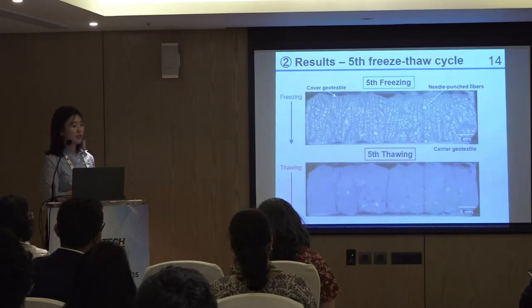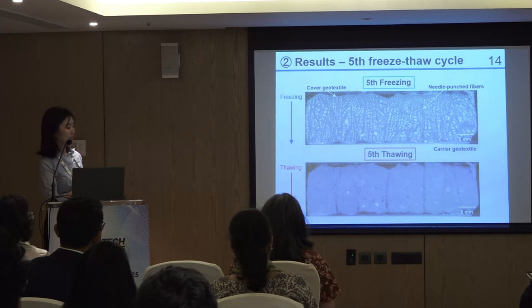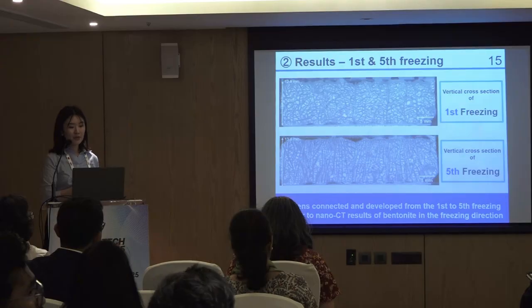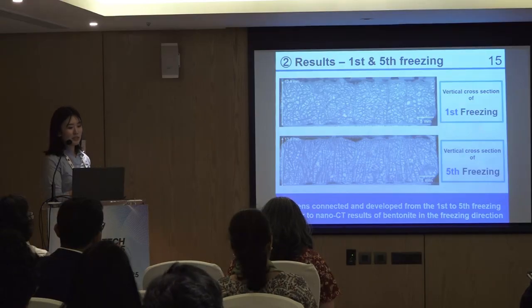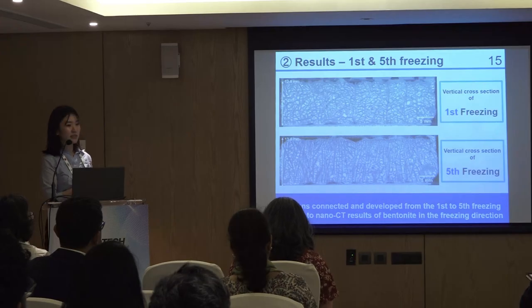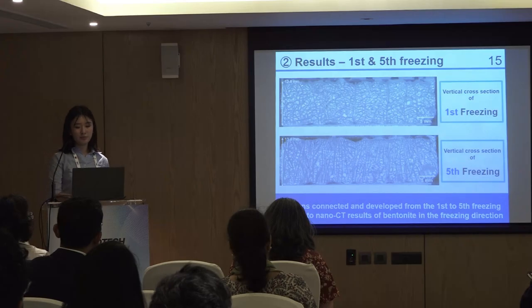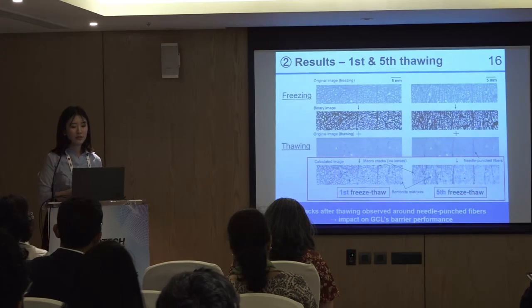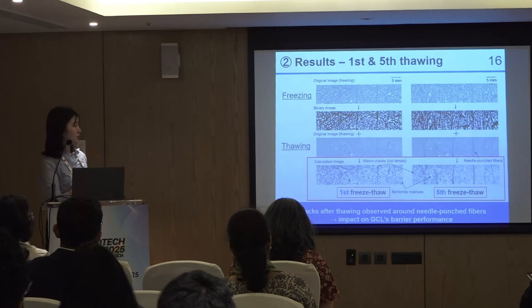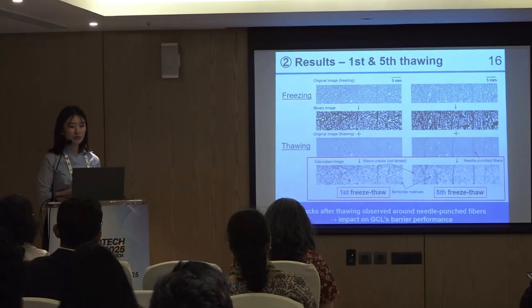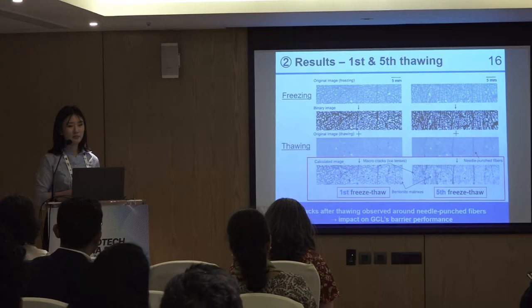And here, these are the images after the fifth freezing and fifth thawing. From the first to fifth freezing, frozen GCL showed a distinct ice lens pattern along the vertical freezing direction, similar to the nano X-ray CT results. Furthermore, after thawing, the cracks were clearly visible along the needle punched fibers. These cracks are expected to have a deep impact on the barrier performance of GCL.